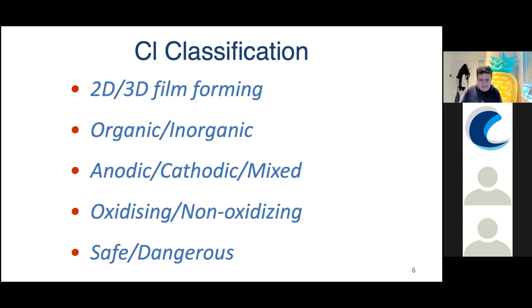They can be either oxidizing or non-oxidizing. And that's referring to situations where there's oxygen, so more near neutral conditions, where there's oxygen in the solution driving the corrosion. It depends whether or not the inhibitor requires that oxygen to function. And finally, there's ones that are described as either safe or dangerous, and that's nothing to do with whether they're explosive or toxic. That means when you change the concentration of the corrosion inhibitor, does the corrosion rate increase gradually as you reduce it, or does it go through a sudden step? If it goes through a sudden step upwards, that's called a dangerous type inhibitor because you must be much more wary of slight variations in concentration.